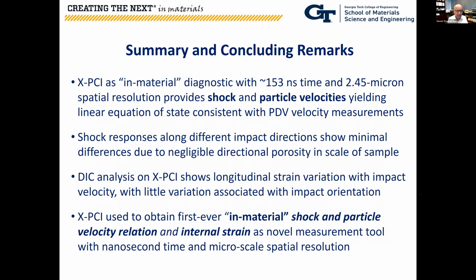Okay, so just to summarize, what I have informed you is, XPCI as an in-material diagnostic is being used to monitor the shock and particle velocities, yielding a linear equation of state, which is consistent with PDV velocity measurements. The shock responses along different impact directions show minimal differences. And I think, as I mentioned, these are due to the negligible directional porosity in the scale of the 2 millimeter span of the sample that is being monitored.